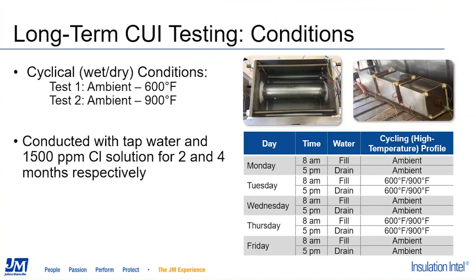So what did we do? We tried to simulate wet and dry conditions over this 6-month period, and we went from filling the vats to draining the vats at temperature and then at ambient. For 2 of the 6 months, the vats were filled with regular tap water, and for 4 of the 6 months, they were filled and drained with a 1,500 part per million chloride solution.